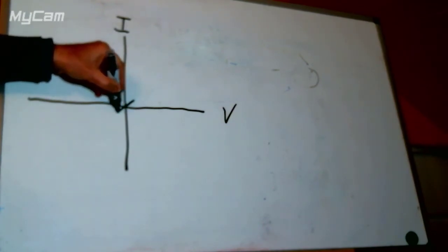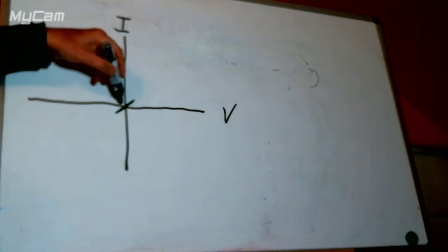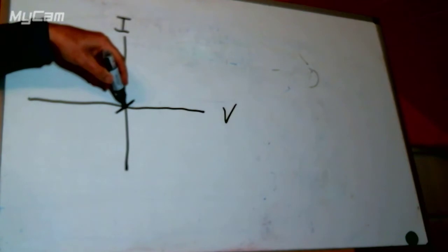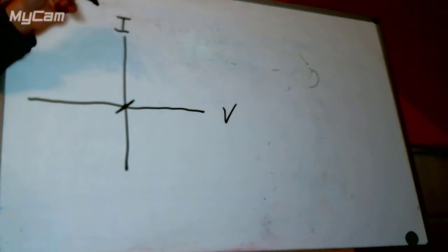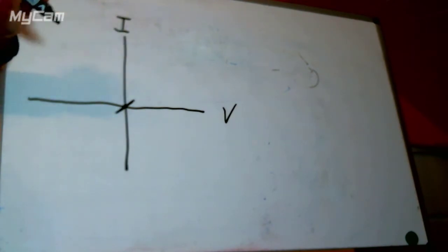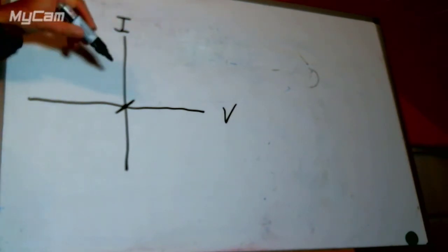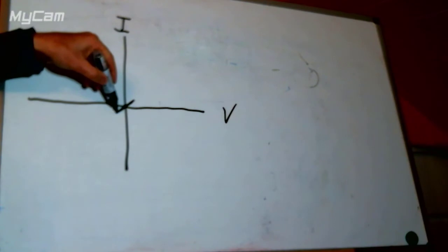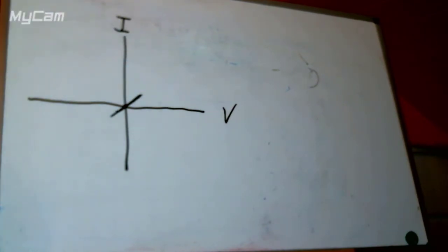We will get some kind of steepness of curve near the 0 voltage. So if we have 0 volts, meaning we just put the electrode in and let it go to the voltage that it wants to go to, obviously the net current is 0 because no current can pass. So if we then force it to that voltage with an external power supply, we will still get 0 current. It's unsurprising. If we make it negative compared to that, we'll get negative current, and if we make it positive compared to that, we'll get positive current.